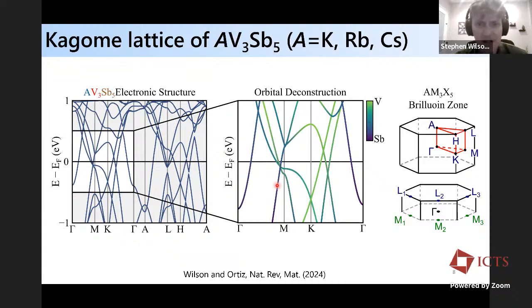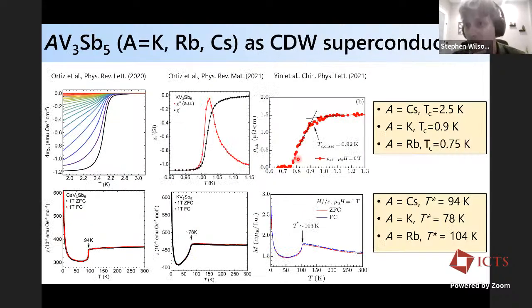But these Van Hove points at the DFT level are very close to the Fermi level, and this motivated some of the initial interest in these systems. And indeed, these systems realize correlation-driven physics. They're charge density wave superconductors. There are three different parent compounds, or flavors. You can change the A site; the alkali metal site can be either potassium, rubidium, or cesium.